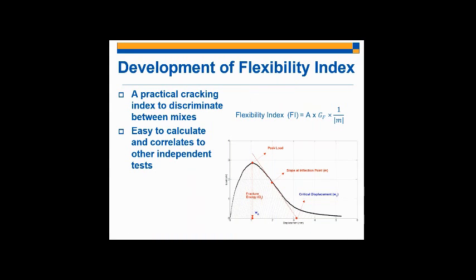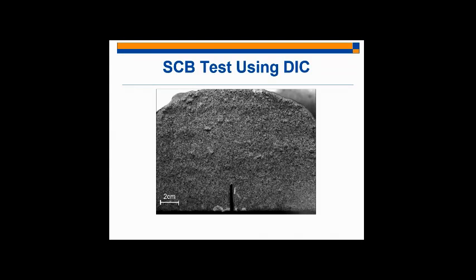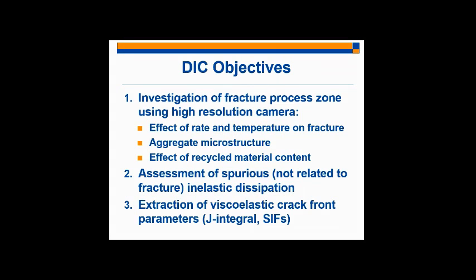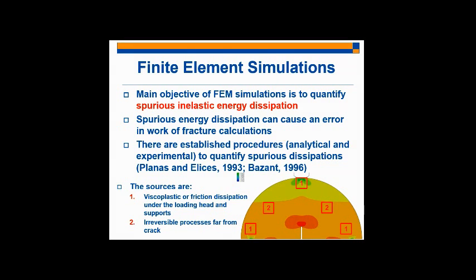And so, again, going back to the development of the flexibility index, having begun to address all of these potential complications that come from 25 degrees Celsius testing temperature, we proceeded to the development of a flexibility index. And I should mention, by the way, that if I can go back here, the FEM work that we're doing has preliminarily shown us that basically these spurious inelastic energies that we are concerned with comprise about less than 10% of the total fracture energy values that we're getting.